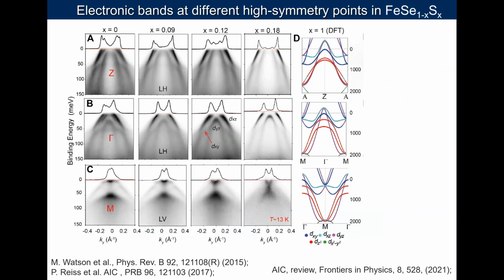Obviously, when we measure the different bands, if we look carefully, there isn't too much change. What really happens is that this inner hole band, which is just about shifted below the Fermi level at low temperature, starts to cut back and go up as we add sulfur. So there are very subtle changes in that inner hole band. And here we can see the dxy band from the hybridization with the other band. This is where it lives, about 50 milli-electron volts below the Fermi level.